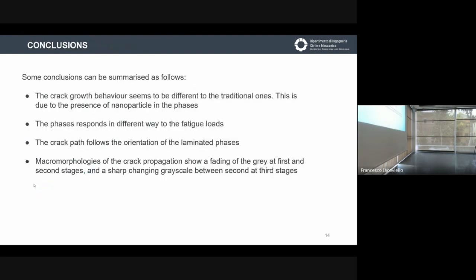So, up to now, we have this conclusion that the crack growth behavior seems to be different from the traditional one in terms of da/dN versus delta K, and it could be attributed to the presence of the zirconium dioxide. The phases respond in different ways. It's normal because the beta phase is much more brittle than the alpha phase. The crack path follows the orientation of the laminated phase. It's obvious.